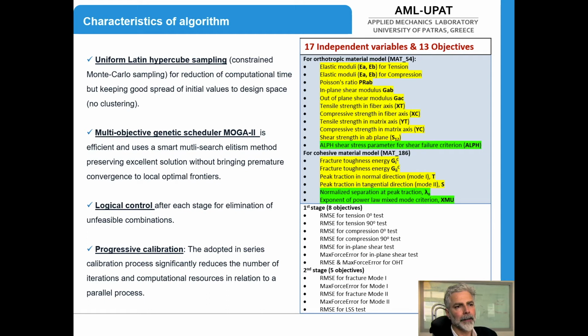In the right part of this figure, you may see the parameters that have been calibrated for the orthotropic material model. And as you may see, further to the typical material properties, we have also calibrated the alpha parameter for the shear nonlinearity. And for the cohesive zone model, the second stage of the optimization scheme, further to the typical values of G1C, G2C, peak traction and peak shear, we also calibrate the normalized separation at peak traction, lambda naught, and the exponent of the power law for the mode mixity criterion.